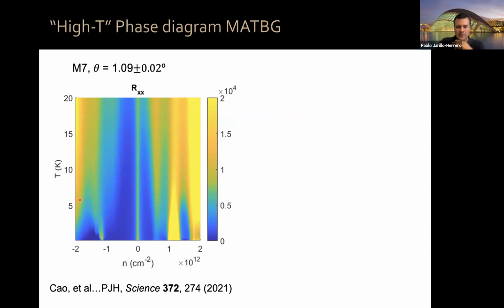Okay, this is the resistivity as a function of temperature, as a function of density. Now as you can see, there are many features here. This is charge neutrality. This is the correlated insulator at 2 electrons per moiré unit cell. This is 2 holes per moiré unit cell. Something happens also at 1 and at 3. I'm not going to be telling you much about that here. Here is the superconducting dome.